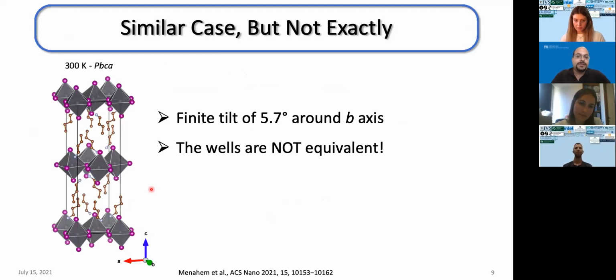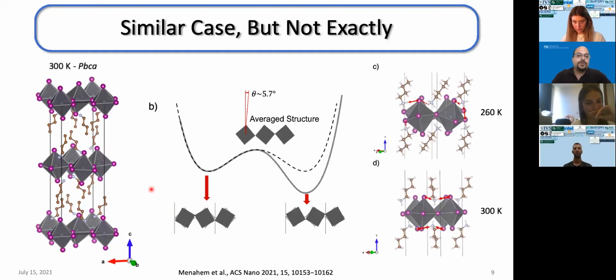If we still adopt the double well potential model, this tells us that one of the wells is not equivalent. And the way we understand it now is that the atoms still feel a double well potential related to some octahedral tilting motion, but one of the wells is more stable than the other one. Now at the high temperature phase, when we average all of these configurations, the average structure is not the untilted one, but a slightly tilted one, giving us back the same symmetry we had at the bottom of the well.